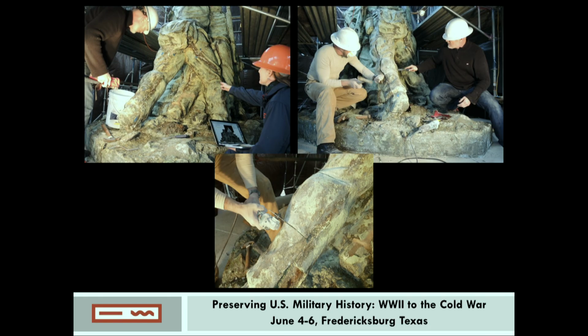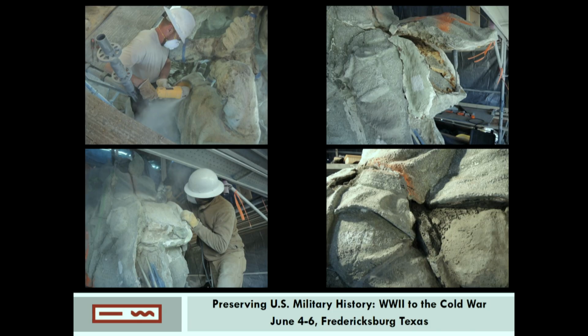the rebar. The internal core and rebar were accessed by cutting through the concrete outer shell using a diamond blade fitted to electric grinders. Registration marks were made on the sections that were removed so they could be reattached in their exact location at a later date. These processes were documented by field drawings and photographs. And you can see Joe and Seth from Conservation Solutions starting to open it based on the X-ray, the areas that we had indicated needed that work. This was not an easy process, as you can gather from the images, owing to the geometry, and on some parts of the sculpture, it was just really difficult to access.